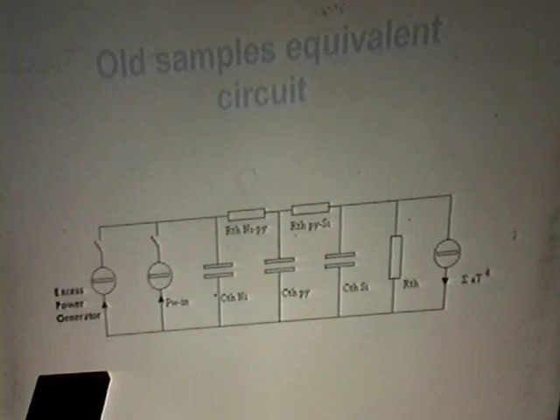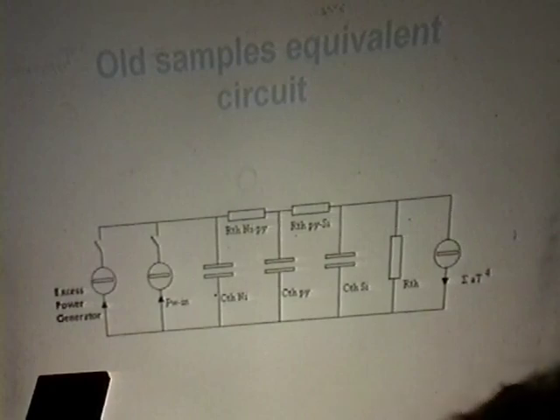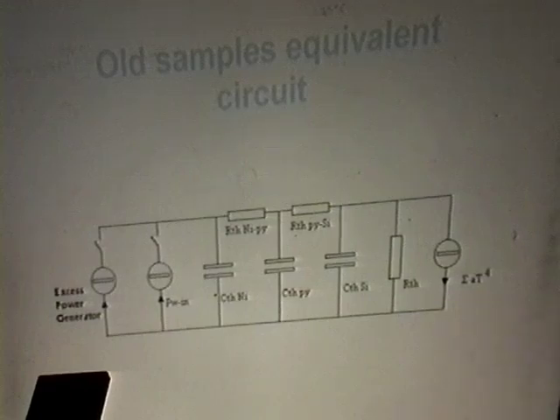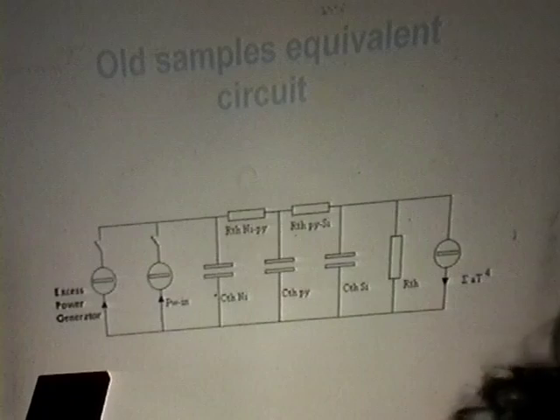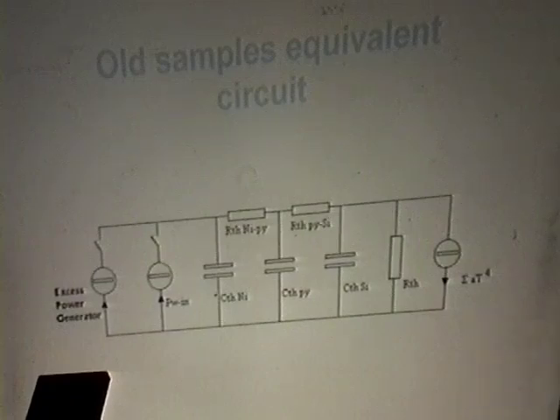at high temperature. The RTH is the thermal resistance of the silicon. The RTH py-silicon is the thermal resistance of the heater, between the heater and the silicon. And the RTH and nickel is the thermal resistance between the nickel itself and the heater. And having a system like this, we have the power in that is able to put the system at